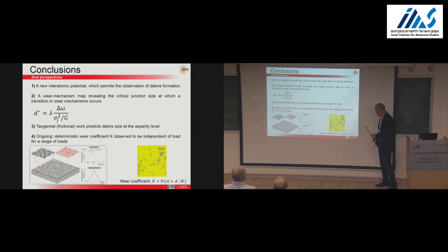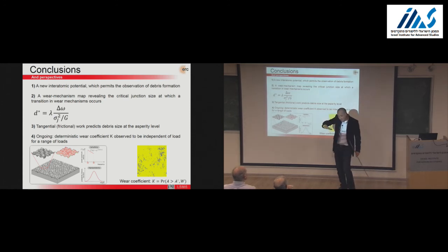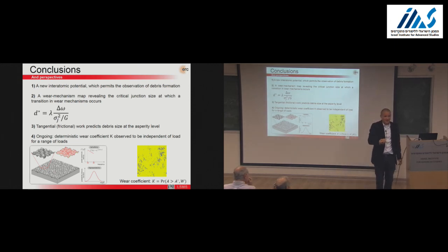And it turns out that experimentally, it's not obvious at all that K is independent of load. As you increase the load, you measure experimentally the same wear coefficient K. And why is that the case? Because the more I push, the more I will bring microcontacts, the more my microcontacts will grow. But we do find in BEM calculations that we have a range of loads for which K is indeed independent of load. And this we need to understand a bit further.